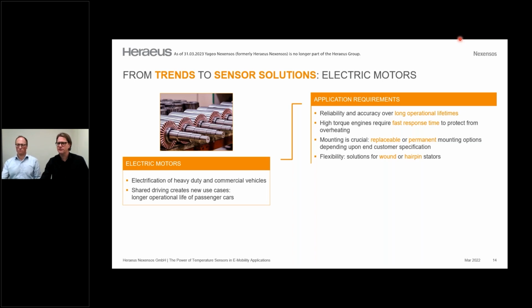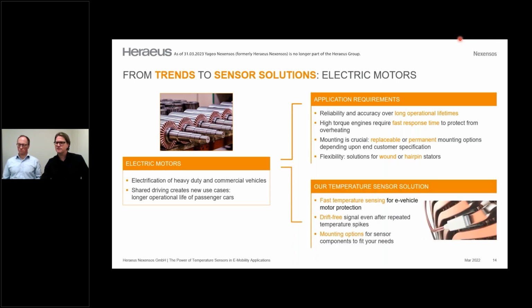The response time is also very, very important. If you think about cars parking with wheels directly at the curbstone, the torque you need to roll over that curbstone leads to very, very high temperatures in a very short time. This is the reason why we need fast response times to protect that complete e-motor from overheating. Because what happens in an e-motor if there is an overheating effect? It destroys the insulation varnish or the lacquer, and the magnetism of the magnetic materials is also in the end destroyed, and this leads to a problem. That means the motor is out of order.